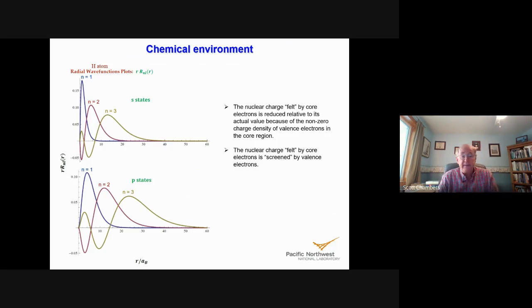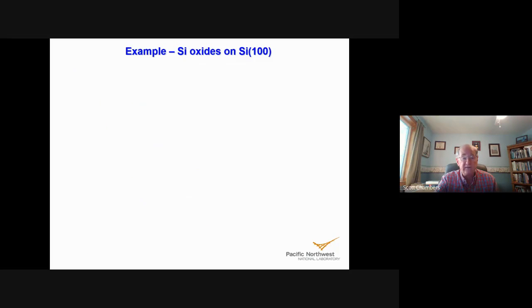Another way you could say that is that the nuclear charge that is felt by the core electrons is screened by the valence electrons. So if you have a change in bonding that results in a change in the valence electron distribution around the photo-emitting atom, and let's say for sake of argument that this change in bonding pulls valence electrons away from the atom, that'll reduce the screening and it'll result in an increase in the deep core level binding energy. And the classic example of this are the oxides of silicon grown on a clean silicon wafer.